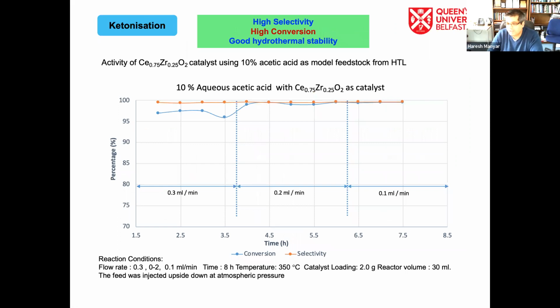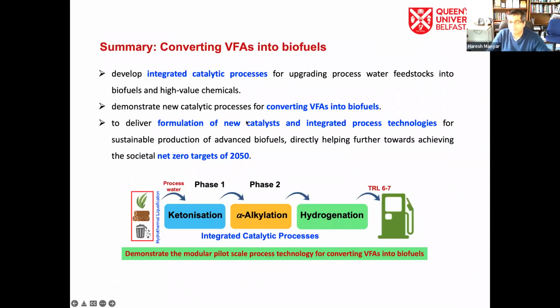And not just acid as an exemplar reaction, we also looked at model feedstocks where we moved into water. We had 90% water present and 10% volatile fatty acids, and we did the reactions with that as well. So the results in front of you here on the slide show that close to 100% conversion and selectivities were achieved with 90% water being present. So again, this shows that these materials have very high hydrothermal stability in the presence of water. And these are really good and stable catalytic materials, which can be used for renewable fuels production, for sustainable fuels. So in summary, metal oxides like sulfated zirconia and mixed metal oxides like ceria zirconia, in the sulfated form, are very good and can assist us in developing cascade type processes for manufacturing advanced jet fuels of renewable origin.